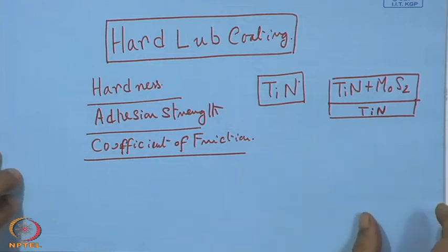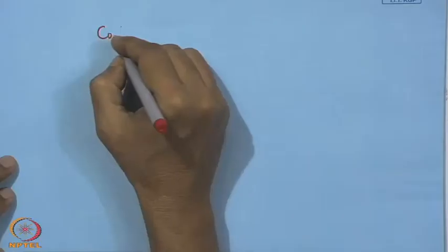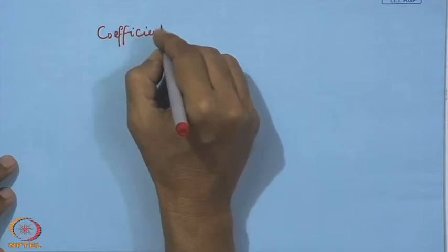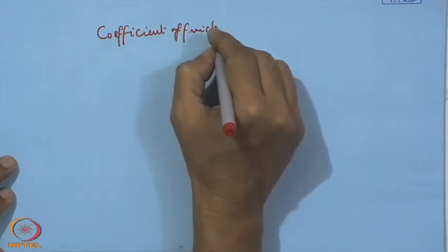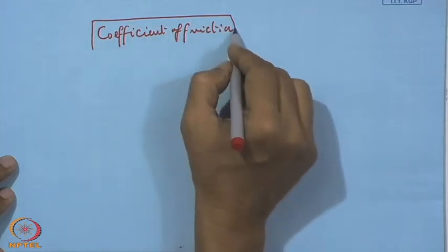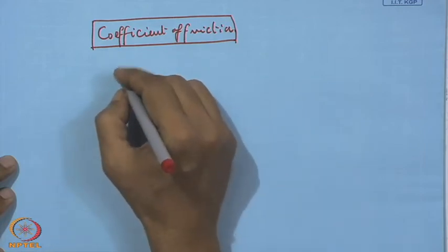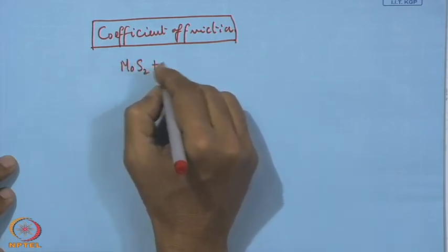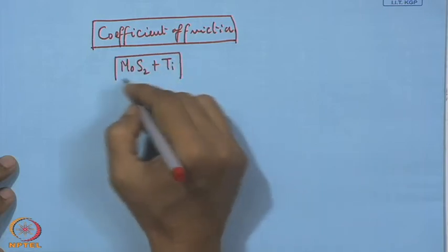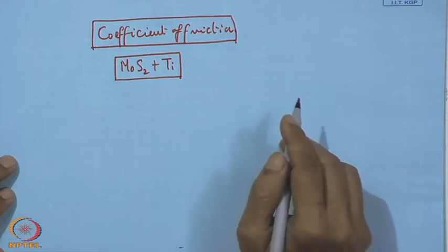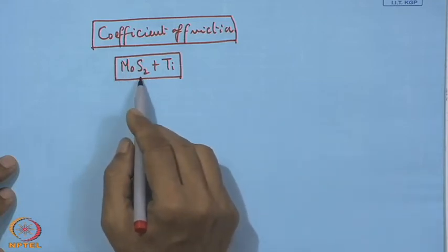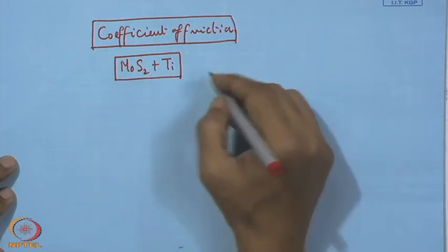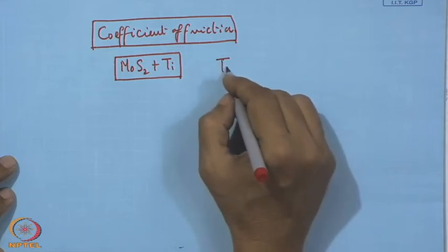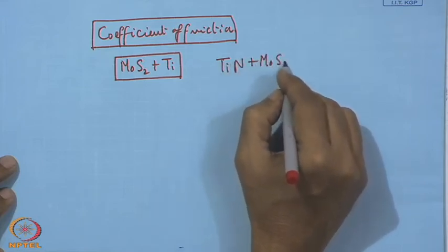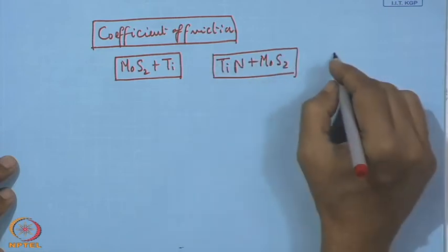But when it is the coefficient of friction, obviously a coating with MoS2 plus titanium, that will be the best one because it is having high percentage of MoS2 and that gives the super lubricity, and it is better than this TiN plus MoS2, and titanium nitride is on the other side.